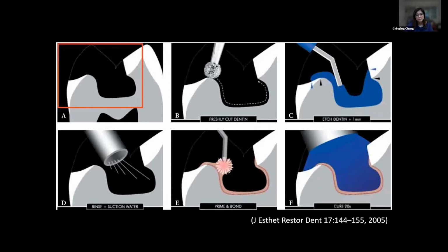This is a picture just showing you how we do it. After we cut the dentin, we etch the dentin surface immediately and rinse out the agent. We apply the primer and bonding, and we apply the glycerin gel to block out the oxygen in the air and cure for 20 seconds. And when we apply the bonding agent, we can still essentially apply the bonding agent on the enamel surface. So what we need to do is slightly prepare the enamel surface after we do the immediate dentin sealing procedure.